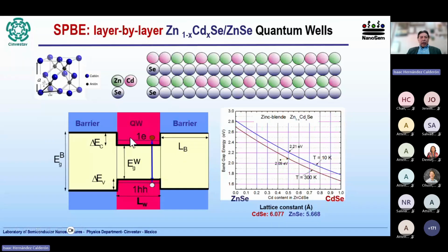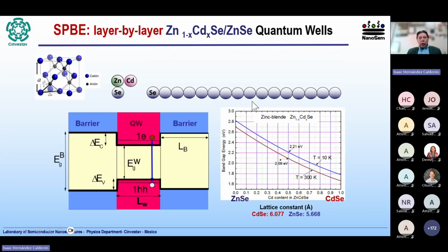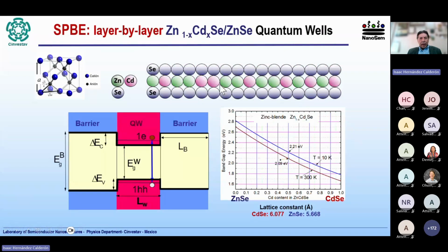Now, in a quantum well, we can tune the emission by modifying the thickness of the quantum well or the composition of the quantum well. If we modify the composition, we can tune the emission, and we can go from the infrared to the UV. So typically, this is the atomic structure of a zinc cadmium selenide quantum well. And this is very well done by MBE and other techniques. However, we would like to do a layer by layer growth, that is cation atoms, anion atoms, in this case, zinc and cadmium, in a fixed proportion, then again, anion atoms, cation atoms. And this was a challenge. How to do this? It's quite complicated, in fact, to try to do that.